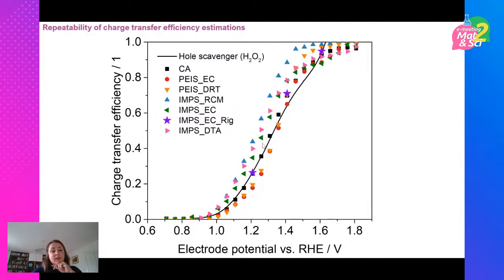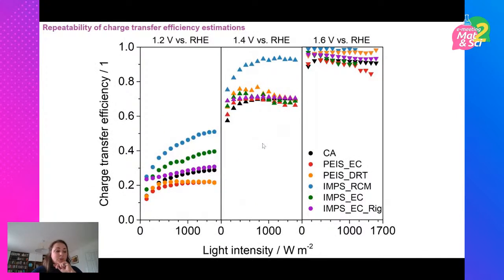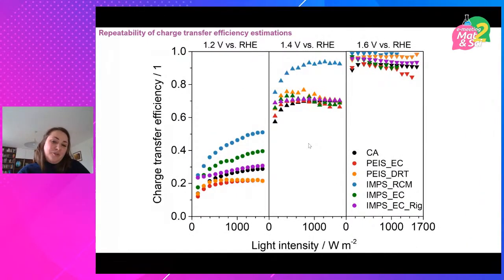glance. So Frankie calculated this as a function of electrode potential, and also subsequently as a function of light intensity. So the accuracy of the technique depends on light intensity and depends on potential. So some techniques that are accurate in one range of conditions are not necessarily the best ones. So having done this for hematite, it remains to be seen how these results might actually compare with other materials.